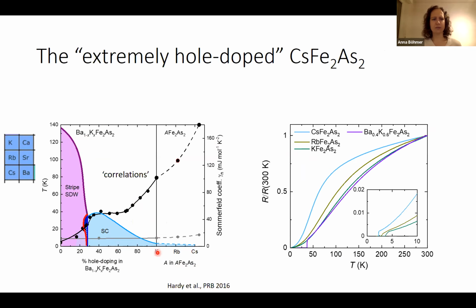We can go further, now vertically in the periodic table, so apply chemical pressure to the rubidium and the cesium compound. And if we go in this direction, we see that the Sommerfeld coefficient, the specific heat coefficient, the effective mass, or a measure of the correlations, goes up quite a bit. So these are very large values. This comes in the region of heavy fermion compounds. The resistance also looks similar to heavy fermion systems. There's a huge residual resistance, and there's this almost quadratic or power-law-like temperature dependence at low temperature here. And there are superconductors around 2 or 3 Kelvin.